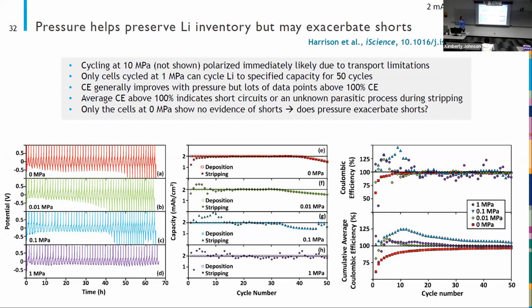Okay, so let's look at the electrochemical results. We, again, are not showing 10 megapascal because we could not run the electrochemistry. And I'll just note that the only cell that was able to cycle continuously for 50 cycles without starting to lose capacity at the end of cycling was at 1 megapascal. So it appears we're getting better performance at higher pressure, but there's a lot of caveats to that.